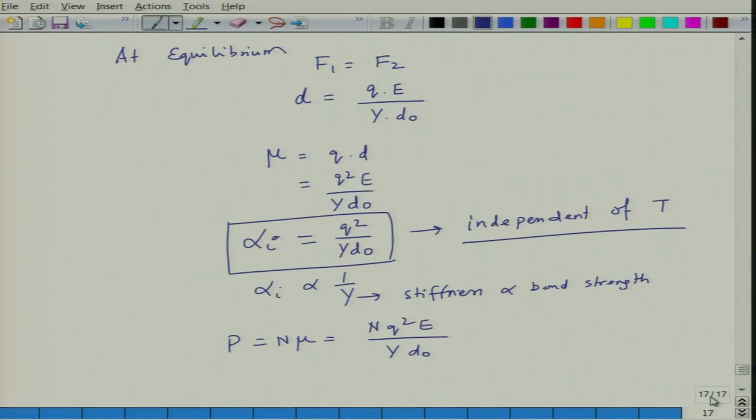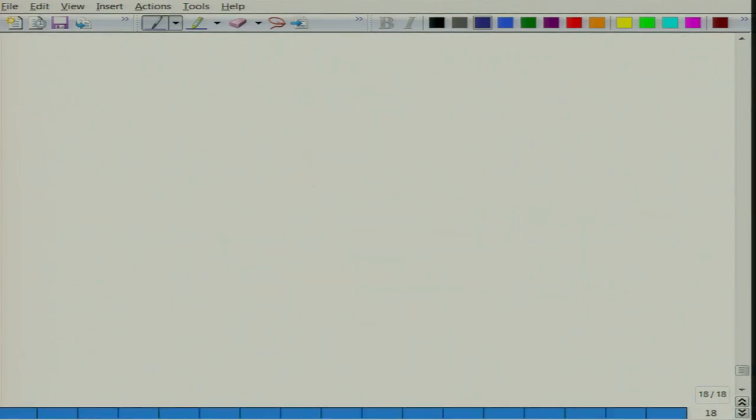So this is basically a very rough guide to calculation of ionic and electronic polarizabilities. If you now compare the values of different materials, for instance ZnO, ZnS, and ZnSe: ZnS has a dielectric constant of 5.1, ZnO is 4.6, and ZnSe is 5.8. These differences are basically because of changes in the bonding characteristics of these materials. So the stronger the material is, the lower the dielectric constant, because the polarizability will be smaller.